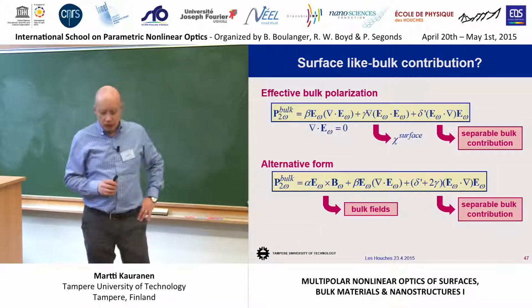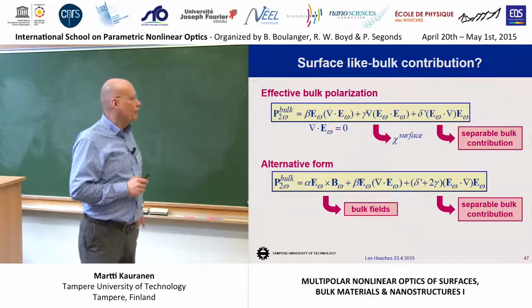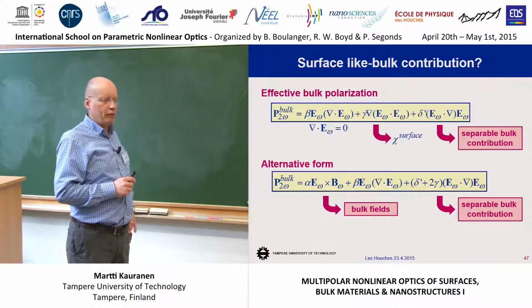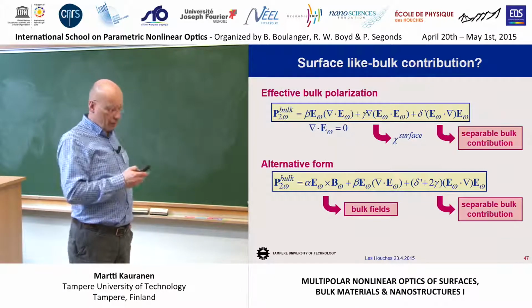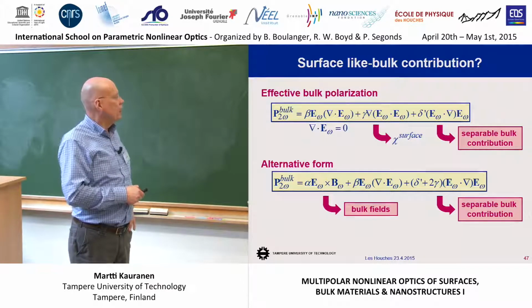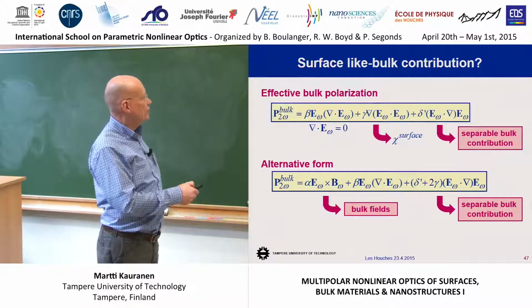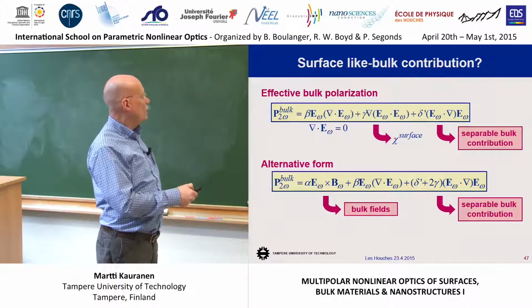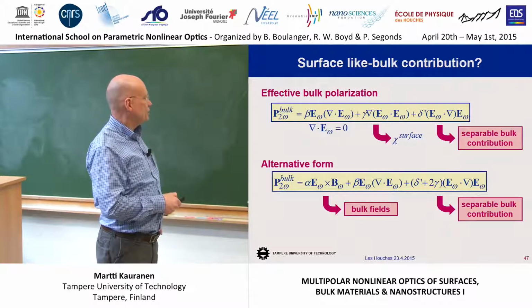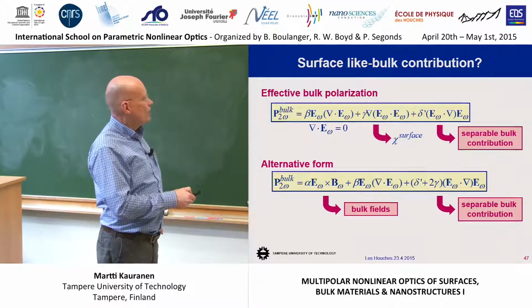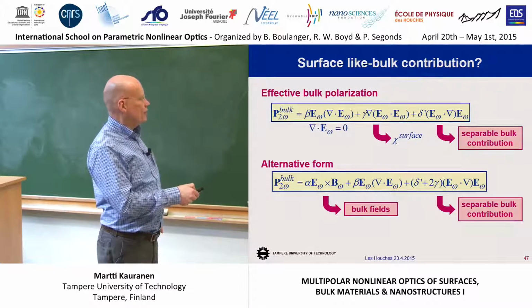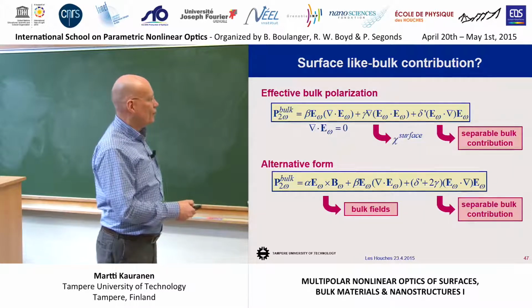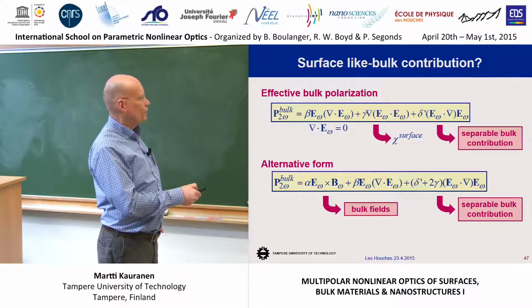mainly used these days. However, if you do some vector differential calculus, or if you go back to the old paper of Bloembergen from I think 1962 or 1963, you find a different expression for the bulk polarization. So basically, this part here can be expressed as a combination of E cross del cross E. And del cross E is actually related to B. So this part contributes a term which is some parameter alpha times E cross B. And then you also get a contribution from here, which looks like this. So you get a modification in the delta prime parameter, which is here. And in the original paper, if I remember right, this was called delta, and when you went to this form, it became delta prime.